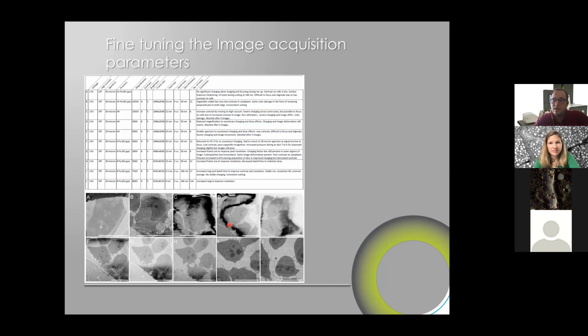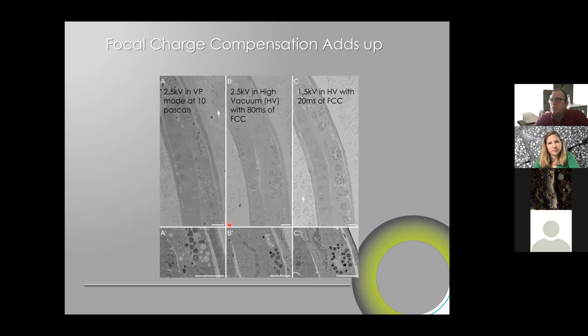And this is something we did together with Jean-Marc Verbavatz and Rémi Leborgne at Institut Jacques Monod. Basically because we were about to launch the product, and then we realized that what we were about to sell was not what we were testing in the lab. So that was quite a stressful period, but we managed to produce on a large scale the exact same product as what we had. And this is when we start to do the next step, which is basically trying to combine fluorescence preservation and volume imaging at the same step.